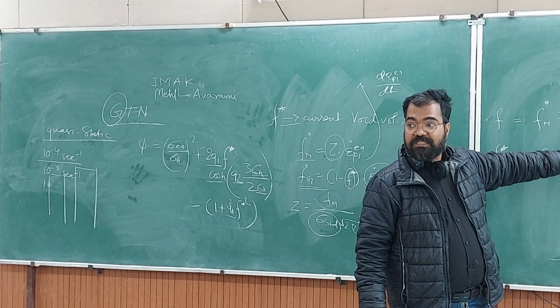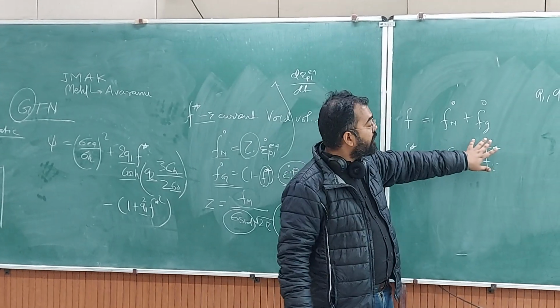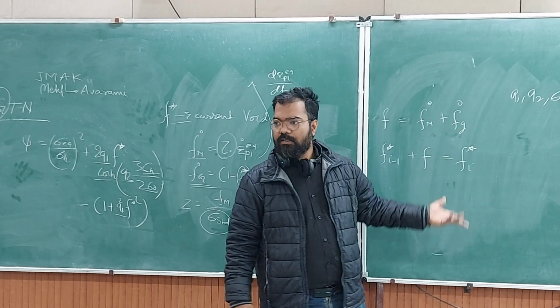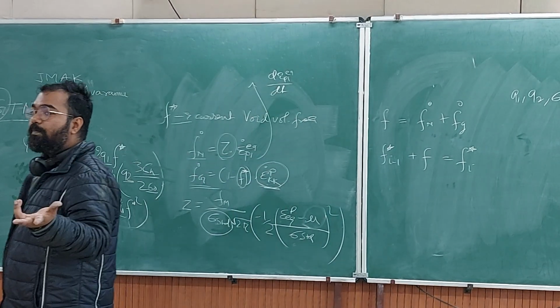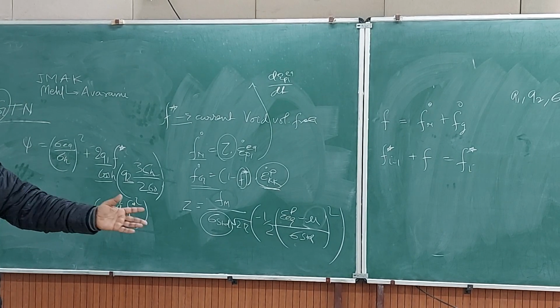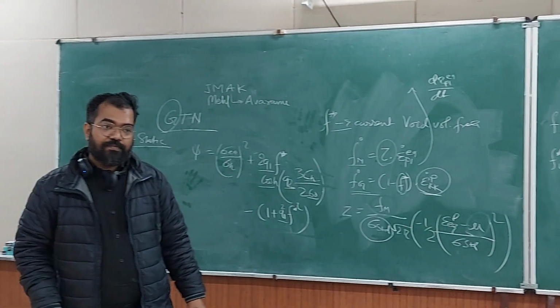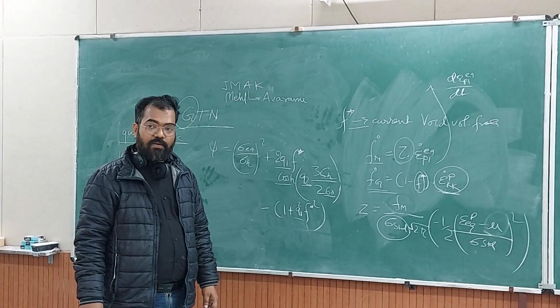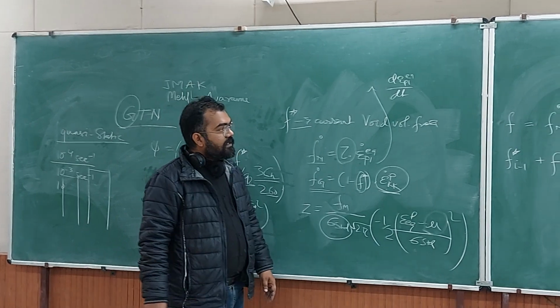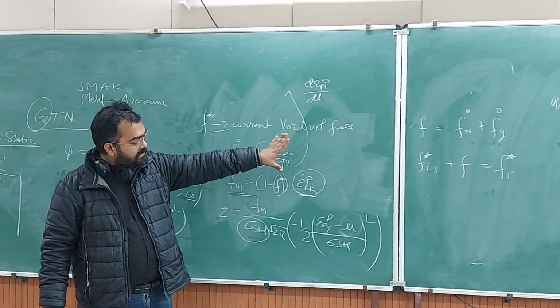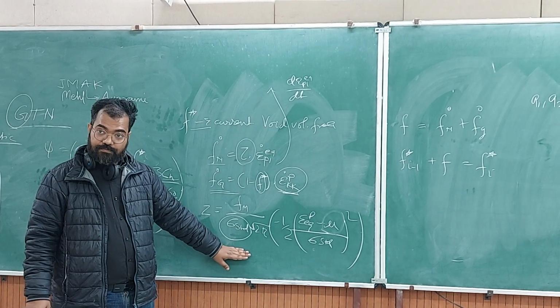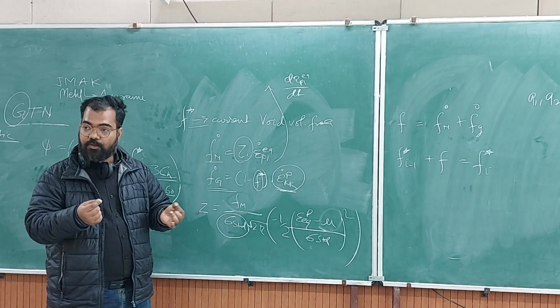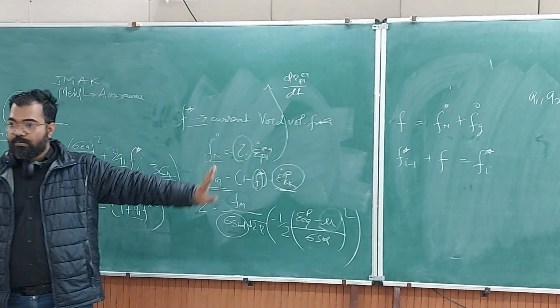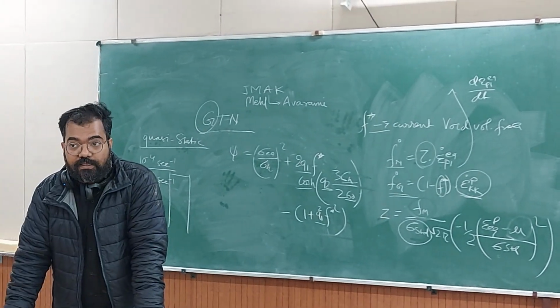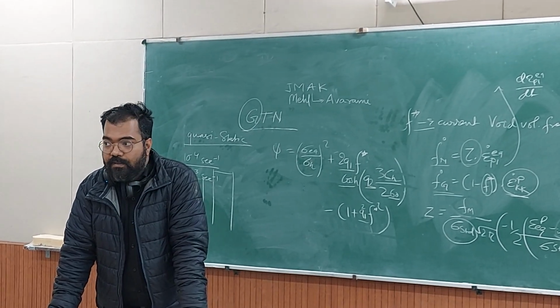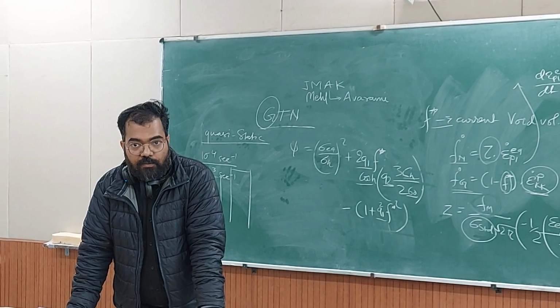Another is that this doesn't look logical. Although if you should say, looking at Avrami, that you just multiply and then things should be okay. Okay? But when you multiply and then simulate, it doesn't match. It is far away from the experiment. It really doesn't work. Okay? So some theory says that the error which is happening in addition there is somehow taken care of in Gaussian distribution here. Because at the end you are fitting these parameters or tweaking these values so that it adjusts to experimental value. Your project problem is to correct this. Okay? You have to correct Gurson, Tvergaard and Needleman model.